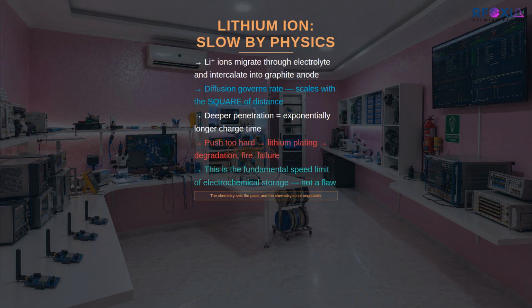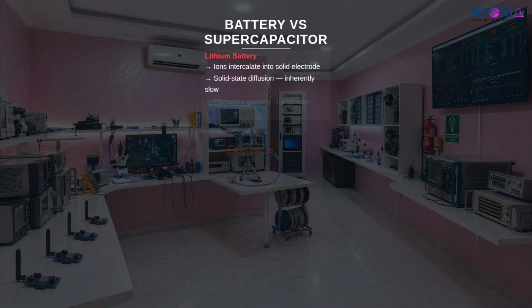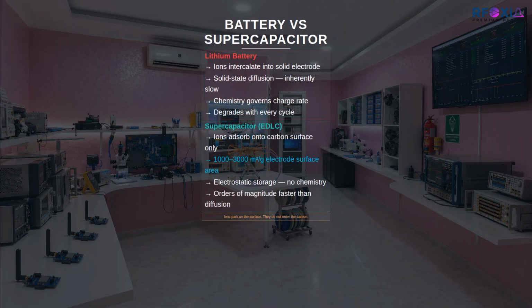This is not a design flaw, it is the fundamental speed limit of electrochemical storage. You cannot charge a lithium cell arbitrarily fast without destroying it, because the lithium ions cannot diffuse into the electrode material fast enough. Push too hard and you get lithium plating, metallic lithium depositing on the anode surface instead of intercalating into it. That is how cells degrade, catch fire and fail. The chemistry sets the pace, and the chemistry is not negotiable.